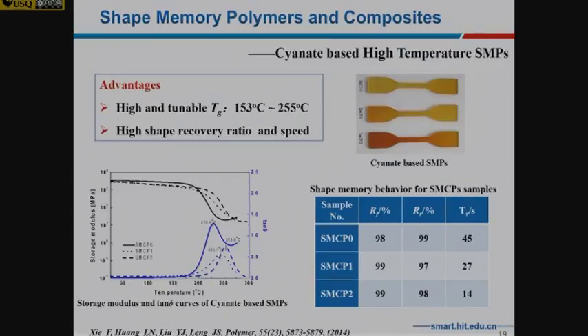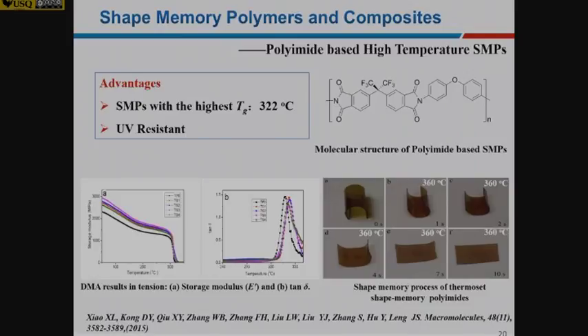So I take some initial published papers to show you what we have done during the last few years. This is a standard cyanate ester based high transition temperature SMP. So the range is around 250. And also we can see the recovery ratio is 98%. So we also produce some polyimide. With the polyimide, you can see the transition temperature is around 320. So this one is also good with the UV resistance. You can see this one with just 10 seconds, the sample can deploy.